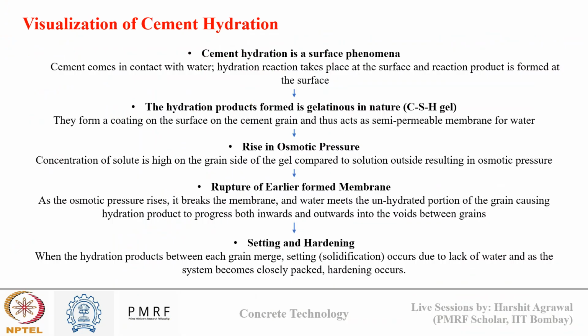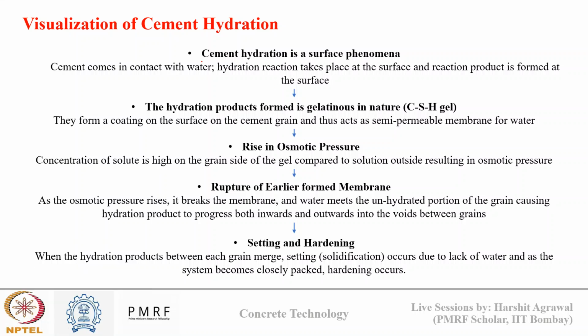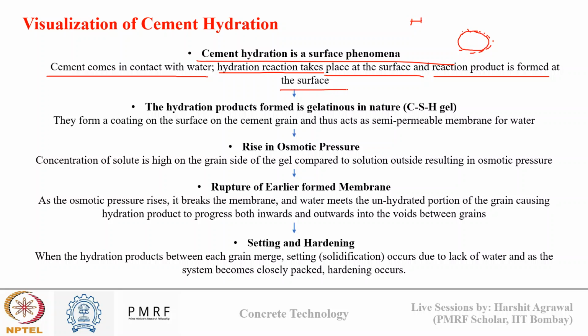Okay, now knowing about cement hydration, let's see a flowchart that describes the process, how it is actually happening on a larger scale. Right now we have seen everything from the microstructure point of view. What about on a larger scale, how is it happening? When we talk about cement hydration, it is a surface phenomenon. So this is my cement grain, this is water. Hydration starts from the surface of cement. Okay, so when cement comes in contact with water, the hydration reaction happens at the surface, and the hydration product forms at the surface of the cement grain. Now which hydration product am I talking about? I am talking about CSH gel.